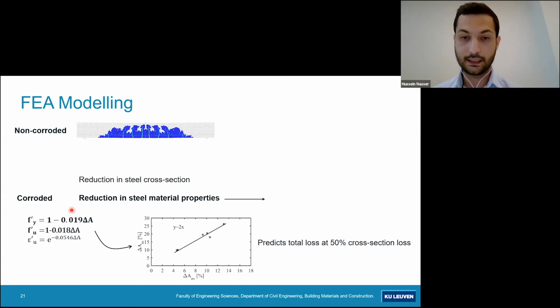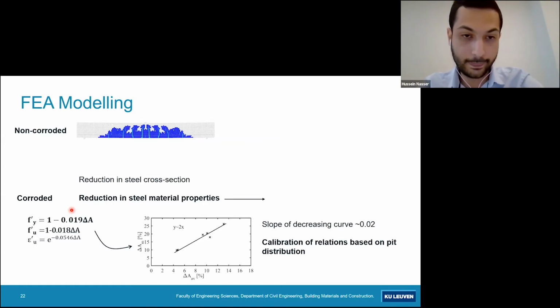Therefore, it predicts that if my average cross-section loss reaches 50%, then at certain location along the rebar, 100% cross-section loss is going to happen. Taking this into account and assuming that the maximum cross-section loss would determine the tensile strength and the yield strength of the rebar, the calibration factors of 0.019 and 0.018 correspond well to the fact that the slope of the decreasing curve predicted from the relation between the average and maximum cross-section loss is 0.02. Therefore, it's important to calibrate damage relations to reduce the material properties of steel based on the distribution of pits.